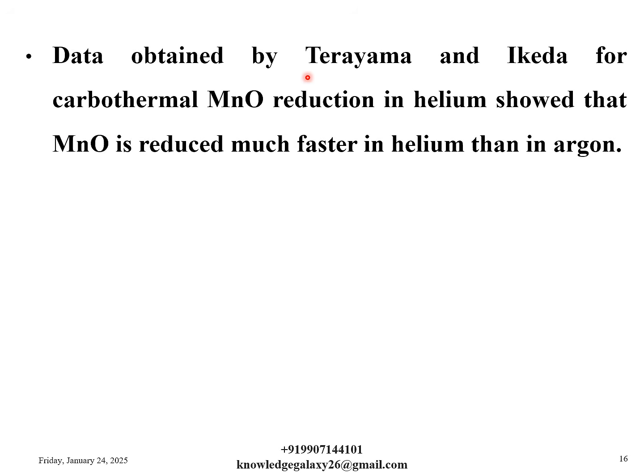Data obtained by Terayama and Ikeda for carbothermal MnO reduction in helium showed that MnO is reduced much faster in helium than in argon. Similar results were obtained by Yastreboff et al. for MnO, manganese ore and ferromanganese slag.